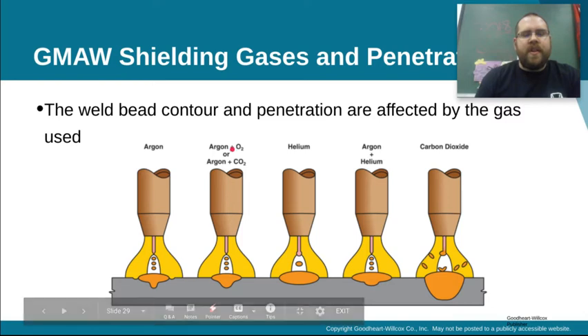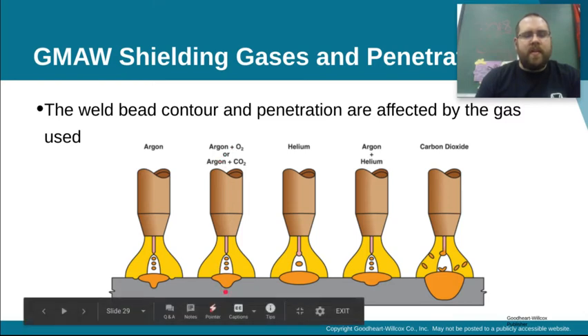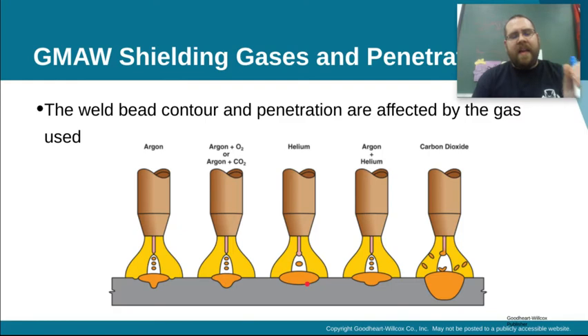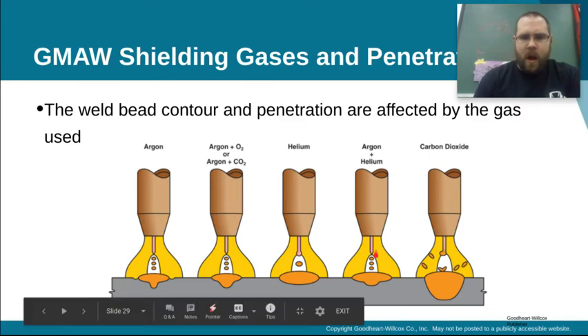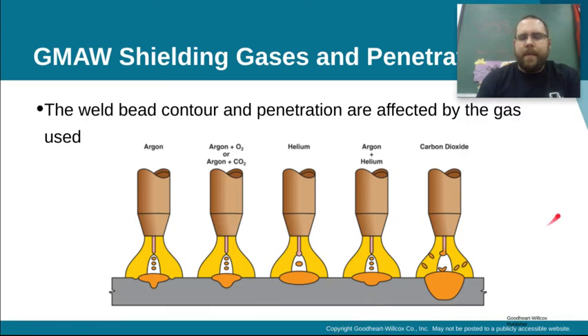Argon and oxygen, or argon and CO2, you get better penetration and no undercut. With helium, you have a fatter, flatter bead. Argon and helium, so it's still a little bit flatter, and you get a lot of penetration. And then with carbon dioxide, you get a whole bunch of penetration, but it causes the weld to spatter a lot more.